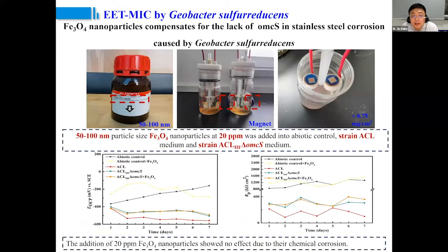And followed by this, we want to fully verify that OmcS play a key role. So we use nanoparticles to compensate for the lack of OmcS in stainless steel corrosion. If nanoparticles can compensate for this, we can double confirm the direct electron transfer in MIC caused by Geobacter sulfurreducens.